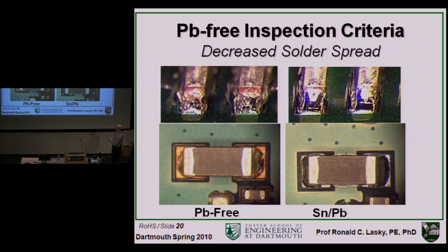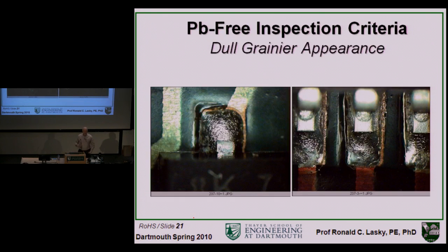This doesn't show as well the fact that this is a tin lead joint, very shiny. This is a little more mottled. I have a better picture here. This is a good lead-free solder joint. This is not cracking or anything. It's just the type of structure that lead-free solder has when it freezes. And so we had to develop in the industry a whole new set of inspection criteria for people that inspect solder joints, because it isn't shiny as a tin lead solder joint.